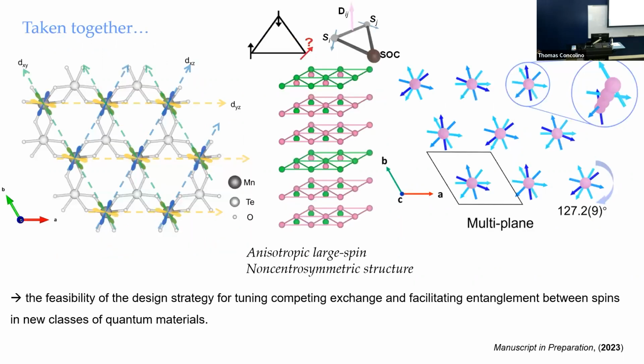Taking it all together, you can see that we can chemically tune the way the spins communicate in this triangular lattice. We have to look carefully to realize it's actually a triangular, not a honeycomb, lattice. And when you can induce a noncentrosymmetric structure, with broken inversion center symmetry, you can then realize the incommensurate magnetic ground state. So it suggests something you can consider as one way to chemically modify the competing exchange, and a way to potentially facilitate the entanglement between spins in a new class of quantum material.